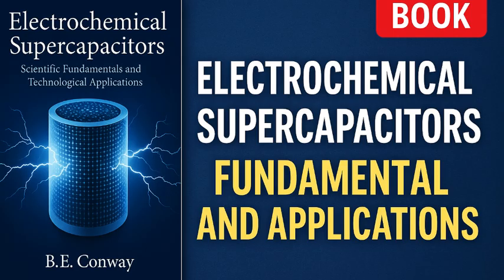Particle size and packing. In a composite electrode, small particles expose more surface but can also pack tightly and hinder ion flow between them. Some designs use mixed particle sizes to create a bit of void fraction for easier ion percolation. Others use aligned structures to make straight pathways for ions. Additives. Sometimes a little surfactant or functionalization helps the electrolyte wet the pores better. Good wetting is crucial because any dry pore is lost capacitance.